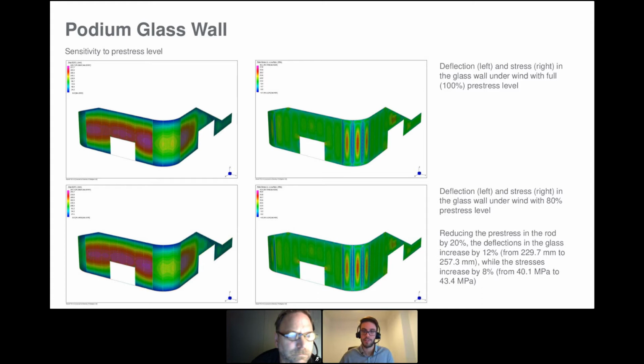So it's also good to make two separate considerations. When we have this accidental pre-stress loss in the rods, it's fair to say that the deflection is slightly higher, maybe even above the criteria, because these are serviceability limit states. So it is acceptable that for this specific scenario, which is an accidental one, we can allow for a bit more deflection in the glass. But what is important to check is that even with this accidental case, the stresses are still within the limits when all the other loads are applied. That was the case here. So when we ran this analysis, the primary check was to make sure that the glass stresses were below the threshold and the strength of the glass, even with this reduced pre-stress level.